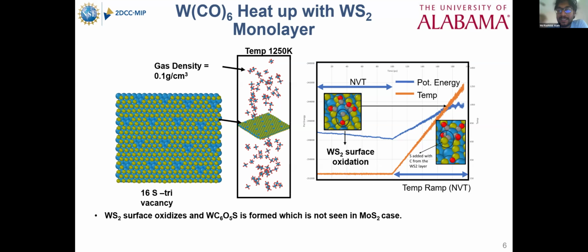But in our case, we have seen that instead of the whole carbon monoxide decomposition, only one oxygen is actually decomposed from the tungsten hexacarbonyl. And this oxygen actually oxidizes this tungsten disulfide surface, and we can also see that at some point later, one sulfur atom from the surface actually gets attached to the gas phase molecules. So we can see that our surface layer actually is being oxidized here, which is not seen in the molybdenum case.